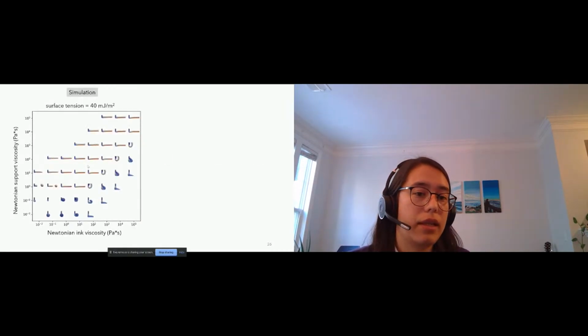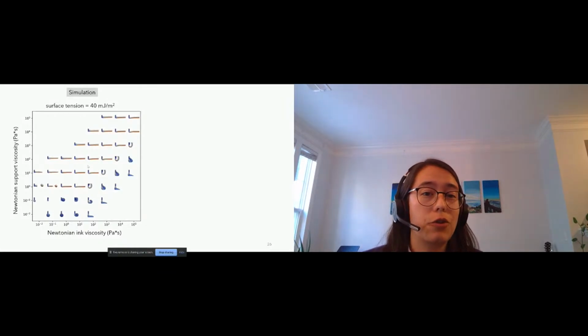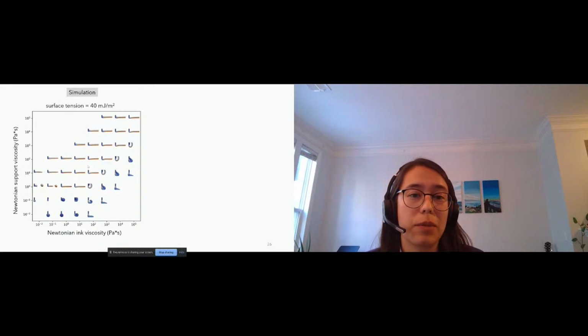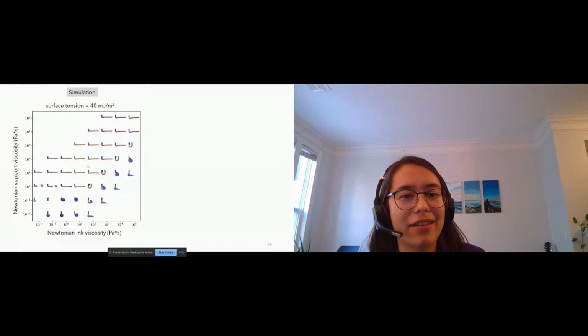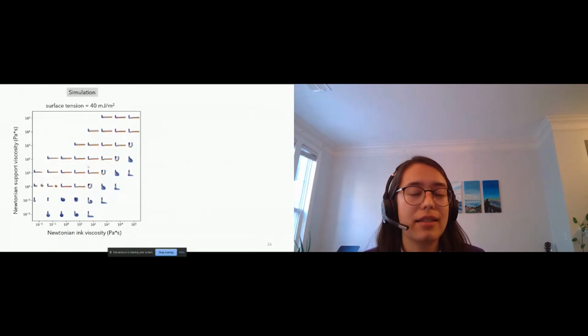So here we're simulating some filaments that are being extruded into a bath at a surface tension of 40 millijoules per meter squared, which is about what you would expect for oil and water. So you can see again, as you look down the diagonals at high viscosities, the viscosity ratio is what is controlling the filament shape here. But as you start to go towards lower support viscosities, we see a little bit of deviation and we see filaments breaking up into droplets or just clinging to the nozzle as